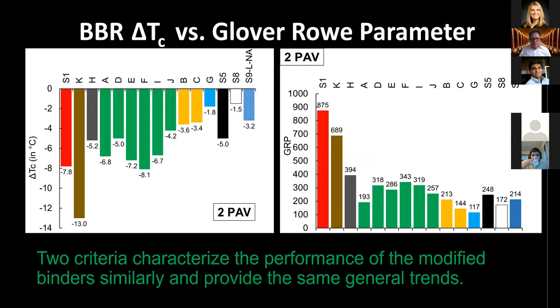So I just described the bending beam delta TC and the Glover-Rowe parameter. As you can tell by these two graphs, the two criteria characterize the performance of the modified binders similarly and provide the same general trends. So what we're saying is these two tests are small strain and give you relatively similar characteristics and performance values of the modified binders.